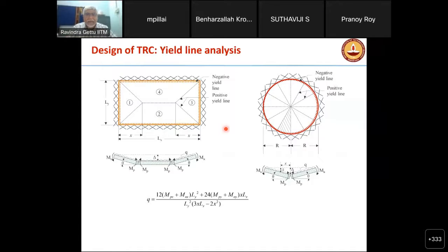With all this, we are confident that we can make elements, we can make structural elements with textile reinforced concrete. And for those of you who have been around for a long time, you will recognize that there is a similarity between this and ferrocement. Long back in the 1960s and 70s, ferrocement was very big. But ferrocement could not be used extensively because of corrosion. And we had to live with metallic reinforcement meshes. Here, we are doing something very similar, except that you are using glass or carbon as the reinforcement instead of metal. Otherwise, the situation is very similar.